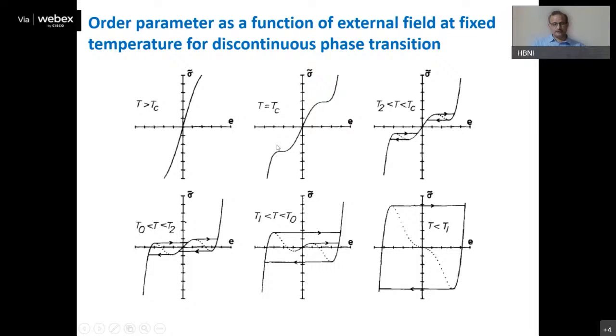Now at T equal to Tc, which corresponds to the second order phase transition, you see this kind of curvature here. This basically describes the instability of the system with respect to the external field. So this is the signature of second order phase transition. Now below Tc, the curves behave like this. Your external field reaches some instability point, and then suddenly the system transforms to some other configuration corresponding to this field versus order parameter relationship. So this is a signature of first order phase transition. As you reduce this external field, the system goes back to the initial phase, but with some hysteresis. So this is a reversible phase transition, but with some hysteresis.